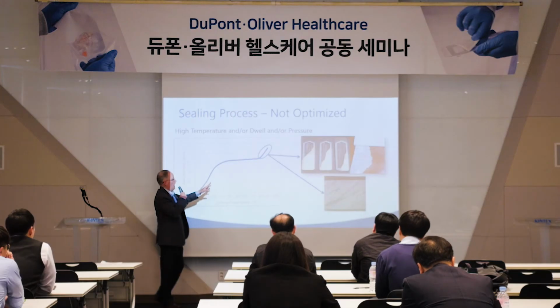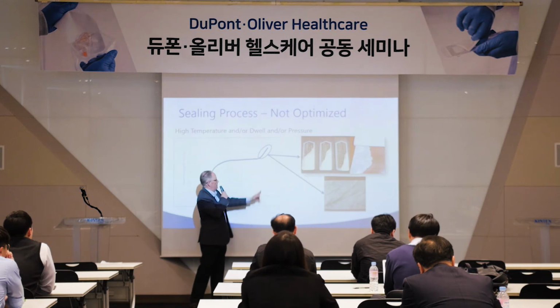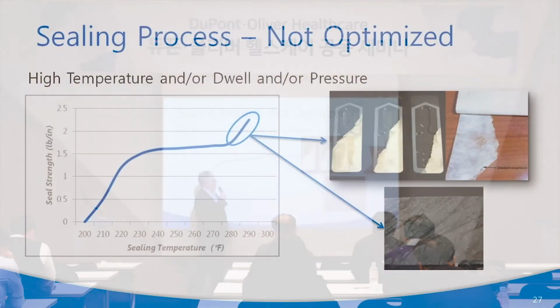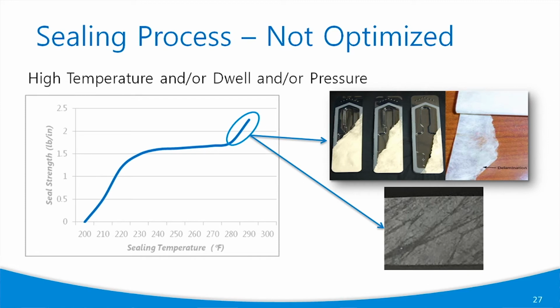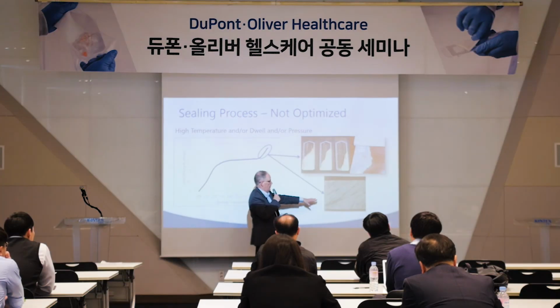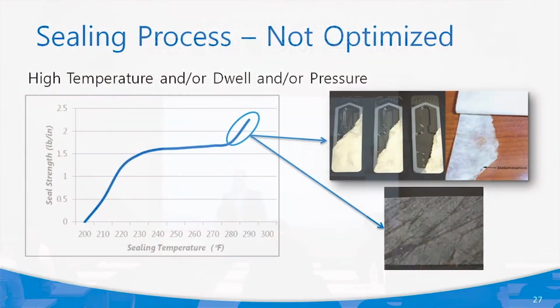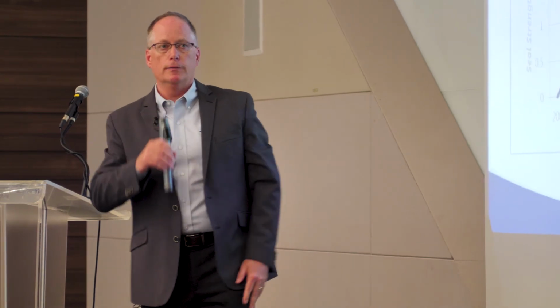So in this slide, we're showing that we're way down here at high temperature, 280, 290 degrees Fahrenheit, and that can cause problems with what you see in the picture. You can get the Tyvek to start tearing. You might be transparentizing the Tyvek, making it clear, so you're basically melting the fibers, and that can contribute to what we're seeing there. And then your adhesive transfer at that upper end can also look kind of differential and spotty. So be very careful to go too high in your sealing process, and we call that oversealing.